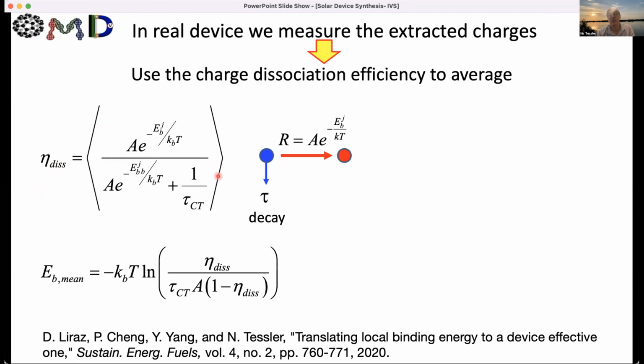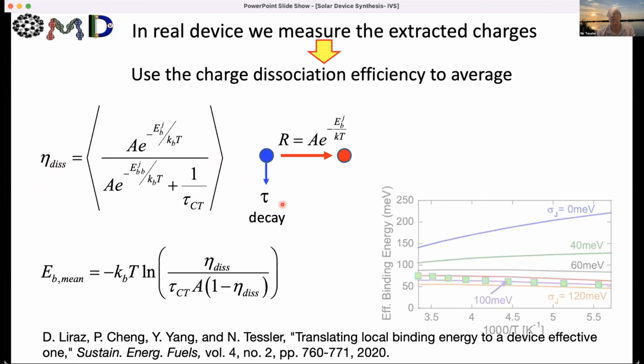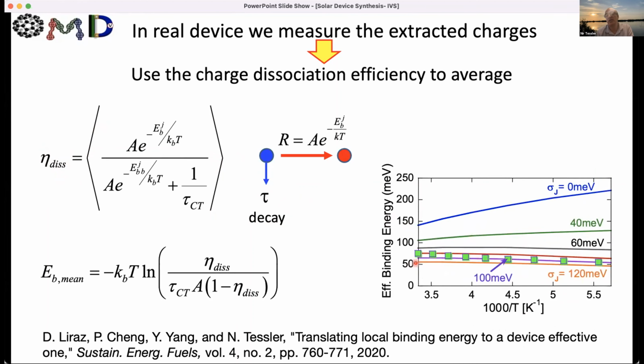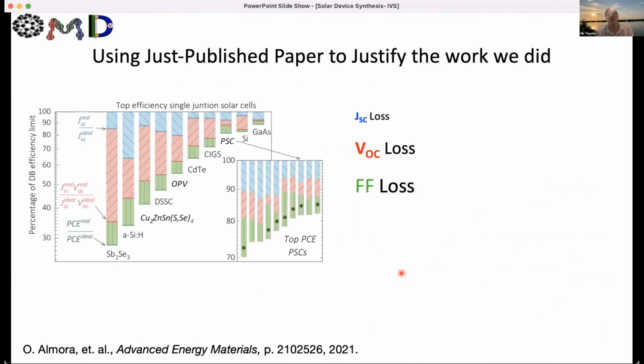And this looks like a minor issue, but it's critical because that's the only reason that Dan managed to show that when he measures devices prepared by our colleagues in the US, he managed to put his model directly on the measurements that he did in our lab using their devices. And this is not an easy thing to do, to get this kind of a model to fit something that is measured from a device prepared elsewhere. And this really changed our focus on this idea and all these studies, that you look again at this new paper and you see that there's not just one color here, there are lots of different losses. So really the approach to look at is to try and maximize the power extraction.